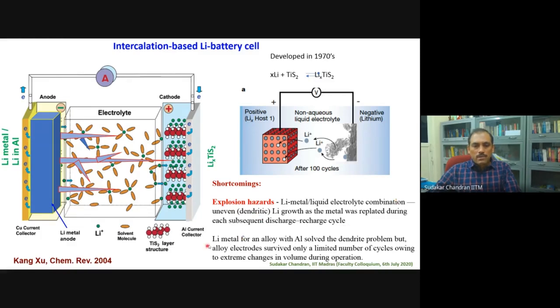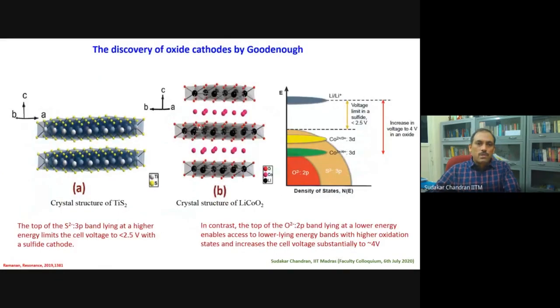To some extent, they tried to mitigate this by using an alloy, a lithium aluminum alloy, but then the cyclability goes bad. There were efforts to commercialize these batteries during the 1980s, but finally they had to drop them because of these fire hazards. This is when Professor John Goodenough's contribution came.